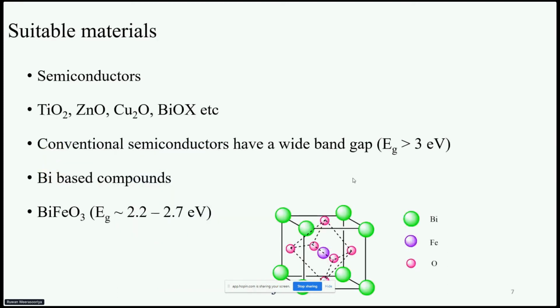Semiconductors were identified as suitable materials to use as photocatalysts. However, the conventional semiconductors have a wide band gap energy which is greater than 3 electron volt. In this scenario, bismuth-based compounds were identified as potential materials to use as photocatalysts. Therefore, in this research, bismuth ferrite was selected as the photocatalyst. It has an energy gap in the range of 2.2 to 2.7 electron volt.